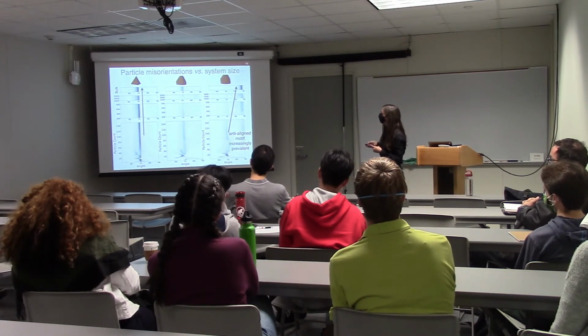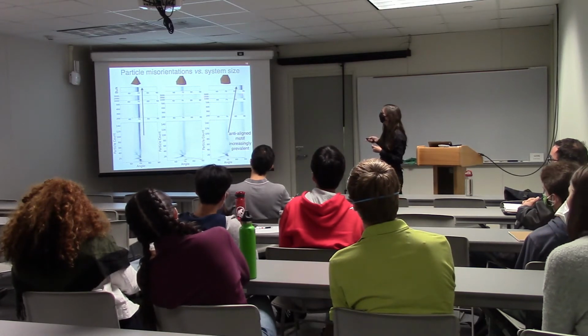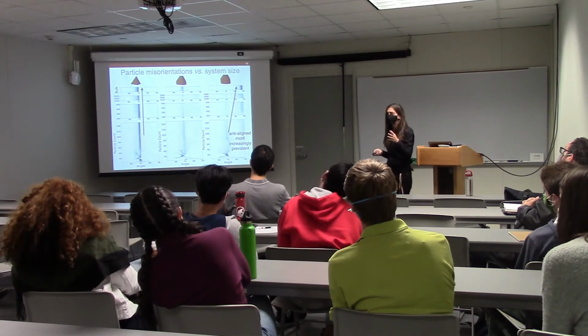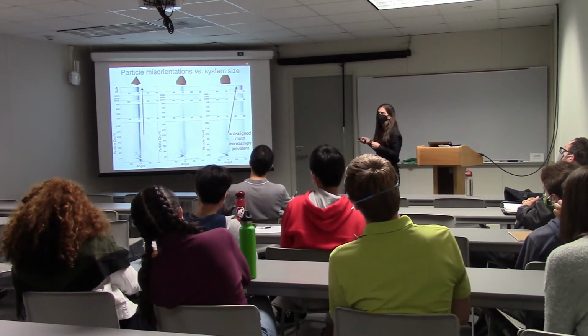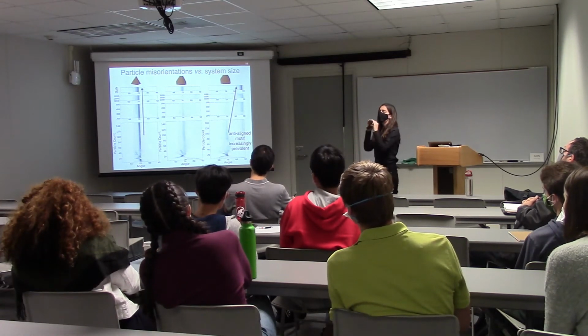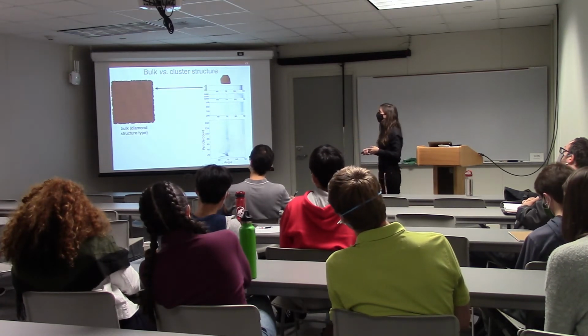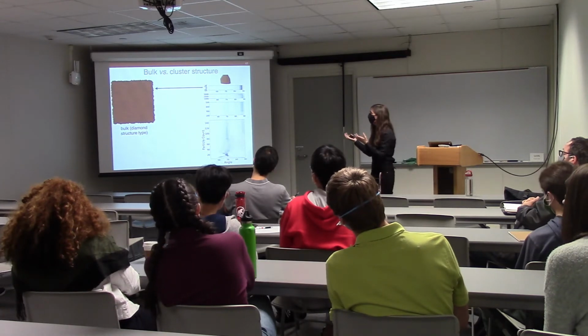For the Archimedean truncated tetrahedra, you see that the anti-aligned motif increases in prevalence, right? In the beginning, it's actually not the most common motif. It increases in prevalence, but even at 3,000, and now we have also measured 5,000 and 10,000 particle systems, it doesn't get that close to what the bulk looks like. So the curvature still has a huge influence on what the particles assemble as, and I will show you an example of what they look like, and you'll see where that comes from.